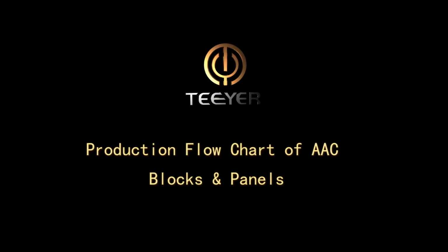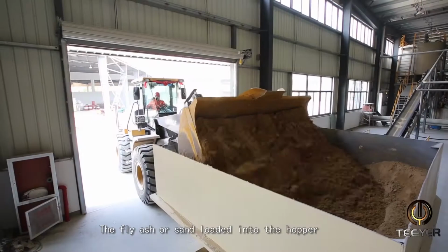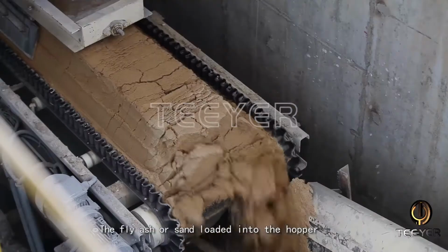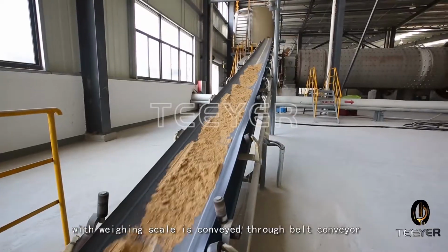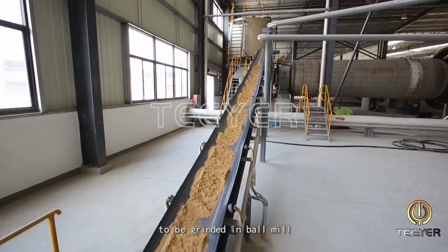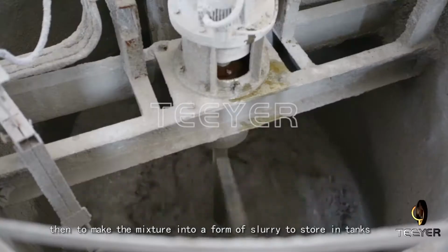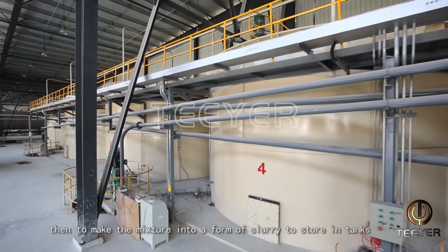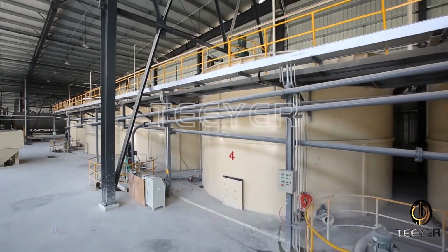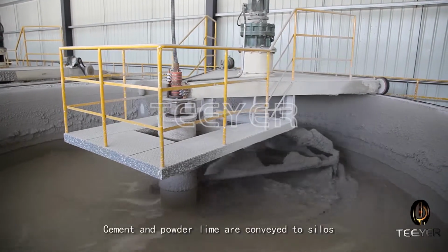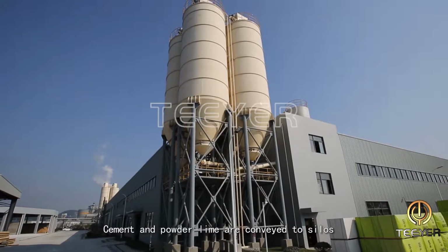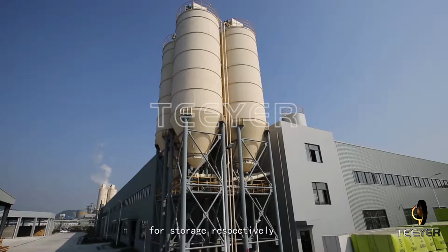Production flow chart of AAC blocks and panels. The fly ash or sand loaded into the hopper with weighing scale is conveyed through belt conveyor to be grinded in ball mill, then to make the mixture into a form of slurry to store in tanks. Cement and powder lime are conveyed to silos for storage respectively.